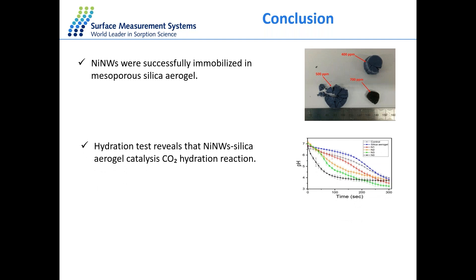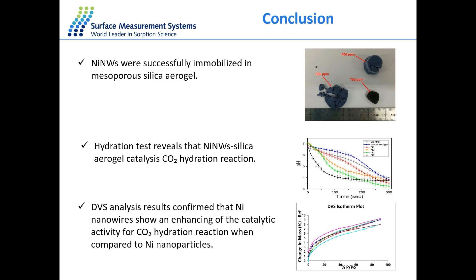In conclusion: we successfully synthesized mesoporous silica aerogel-supported nickel nanowires. The hydration test revealed that nickel nanowire silica aerogel catalysts catalyze the CO2 hydration reaction, with the highest loading of nickel nanowires giving the strongest catalytic activity. DVS analysis confirms that nickel nanowires show enhanced catalytic activity for the carbon dioxide hydration reaction compared to nickel nanoparticles.